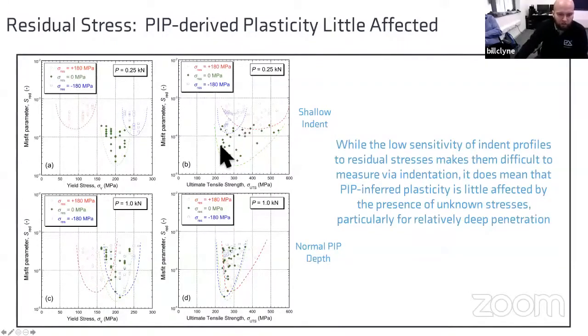As for the UTS, which should be around 260, we can see that there's a very large spread, and this value can go up quite significantly. So that's all for the shallow set of indents. In the deep indents, the effect is much less, as we might have expected. The effect is much less marked.